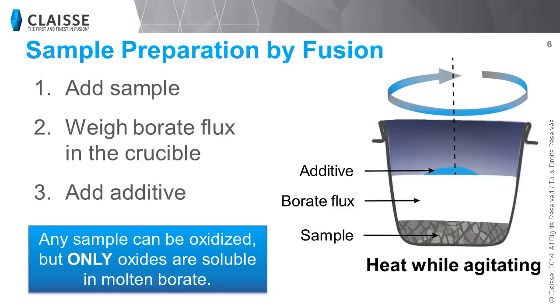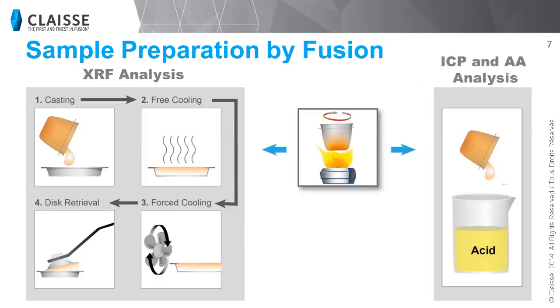You heat up this mixture to melt the borate flux and have the sample dissolved into it. Note that only oxide samples can be dissolved into the borate flux. However, any sample can be oxidized using an oxidizer or an oxidizing technique. Now, once your sample is dissolved into the molten borate flux, you have two options. You either pour the mixture into the platinum gold casting mold or into a diluted acid solution.